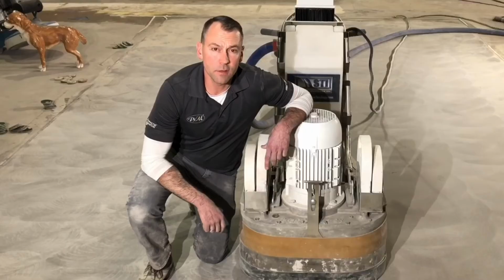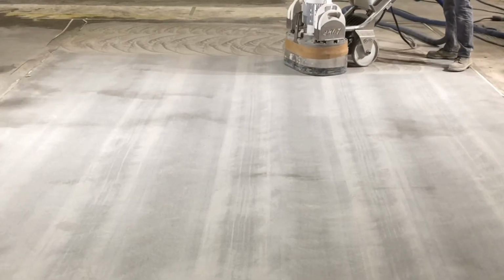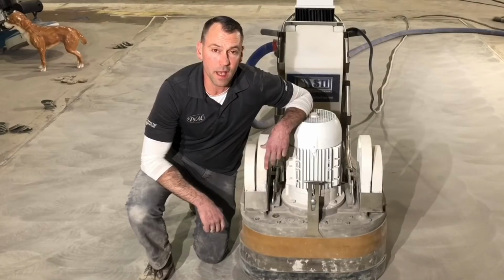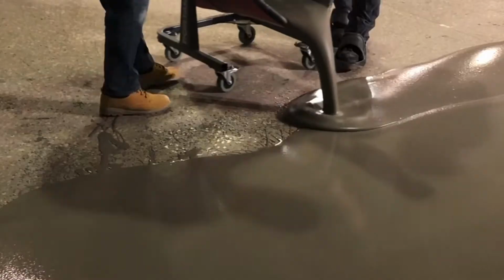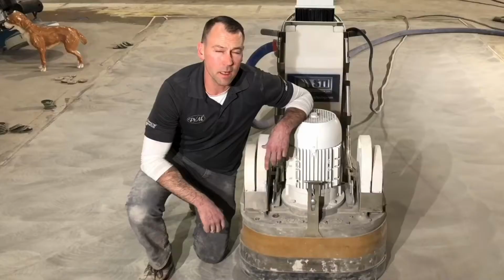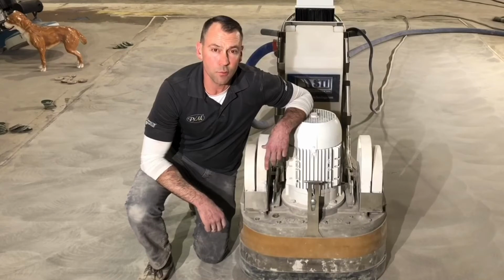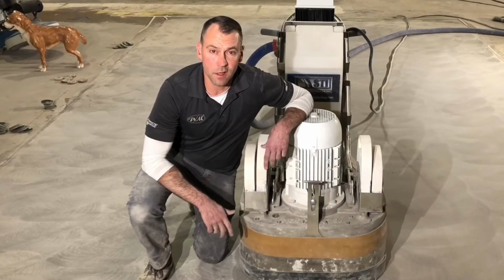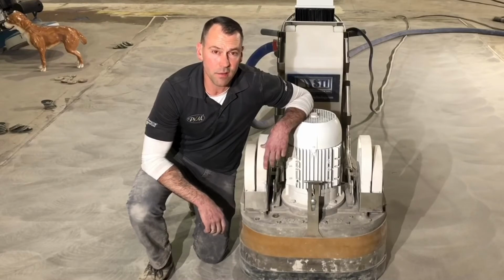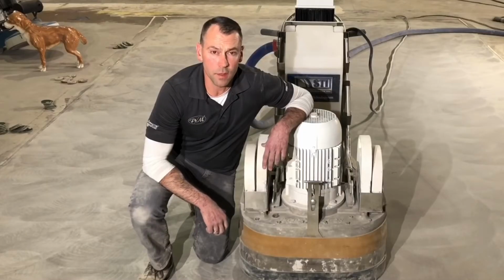As we started grinding with the 16 grits, we found that during installation, there were areas where the material from one pour to the next had begun to dry, and when the next pour was brought in and dumped next to it, we didn't get it blended in very well with the material that was poured previously, in our case about 5 minutes before, so we had problems with seams or pour lines. The pour lines wouldn't be a problem if this floor was going to be covered in carpet or VCT, but because this is a polished slab, whatever the floor has as far as color variation, it's only going to get worse and more noticeable as the floor becomes polished.